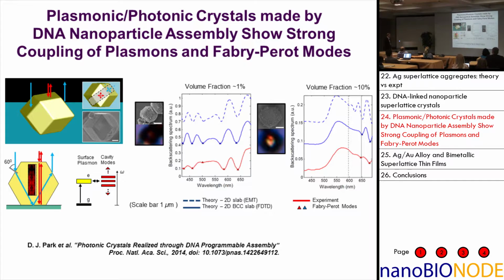and then the light can get trapped between two different crystal faces of this crystal, and that leads to Fabry-Perot modes. If it were just a dielectric material inside of this crystal, then you just get a series of more or less equally spaced lines in the spectrum, and you see some of that here. The red here is experiment. The blues are two different versions of theory that we did for this, and you see a bunch of lines that are well defined. But right here, about 520 nanometers, all of a sudden the line that should be there is gone.